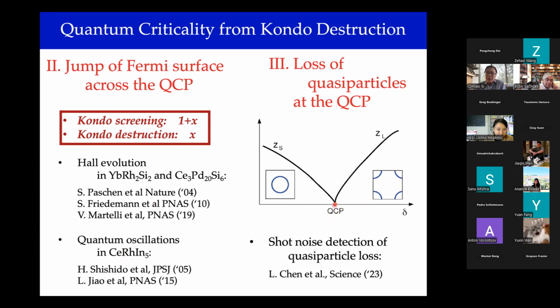And finally, one could ask, how could the Fermi surface jump across a continuous zero temperature phase transition? For that to happen, the quasiparticle weight has to go to 0 at the quantum critical point. And so there's a complete loss of quasiparticles on the entire Fermi surface. About 10 years ago, there was some degree of evidence based on the Wiedemann-Franz ratio measurement, thermal conductivity forming a ratio with electrical conductivity. There's evidence for about a 10% level of violation, but the more decisive evidence came only recently through the shot noise measurement done here in the collaboration between Rice and Vienna University of Technology.